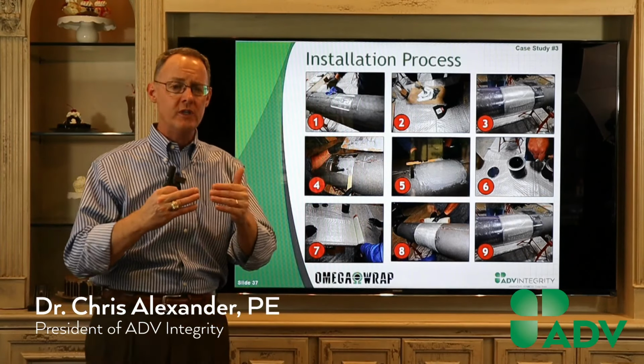So what you see here on the left is the e-glass system. In order for us to get to the actual yield strength of this material, we had to get to about 2,800 PSI. And what you see down here on the bottom is we got to 3,379, so almost 3,400 PSI. And at least in this one, we wind up having a leak underneath it. So the bottom line, we got all the way up to pressure.